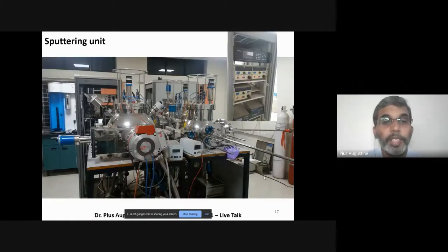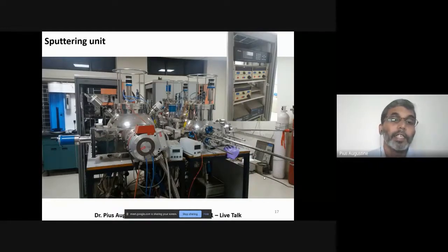This is the sputtering unit which we are using in IISc Bangalore. In this sputtering unit, on the left side, there is a big chamber inside which we load the substrate, and it will be evacuated before deposition, and we have the provision to heat it. Then argon gas will be made available inside, and a very high electric field will be produced. When the high electric field is produced, argon will be ionized, and these ions will be moving at very high velocity because of the strong electric field. And these moving ions will hit the target, and species will be released. That species may be directed towards the substrate, and it will get deposited.